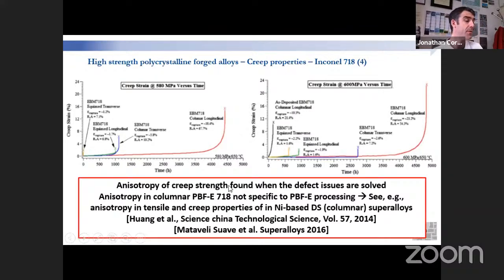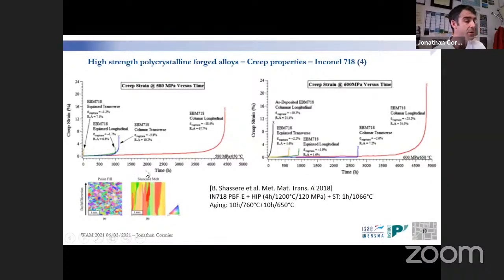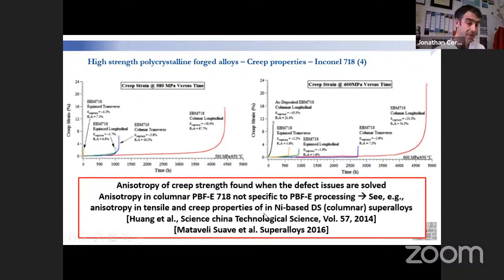This kind of anisotropy in creep strength, which has been found for both PBF-E but also PBF-L processing, is not something specific to this class of processing. I mean, it's not specific to AM, that's really specific to the columnar type microstructure or directional type microstructure we have, in which we know that if we don't have any particles or something specific that will strengthen the grain boundary, we have a lack of ductility overall, and that's something which is well known in the literature for directionally solidified cast superalloys.